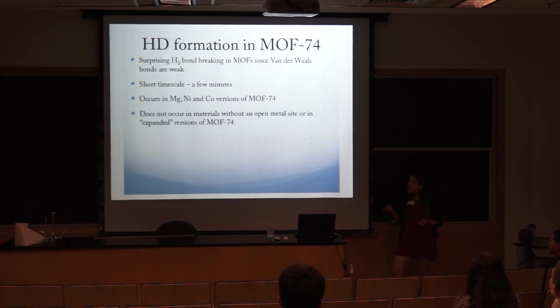MOF-74. Interestingly, it doesn't occur in materials without that open site, the open metal, so materials where the metal is bonded to 6 different atoms, that doesn't happen, so that's cool. And it also doesn't happen in materials that are an expanded version of MOF-74, where basically the metals are further apart because there are 2 benzene rings instead of 1.